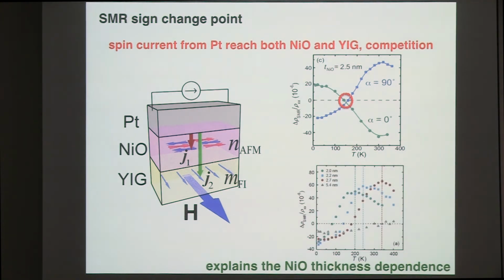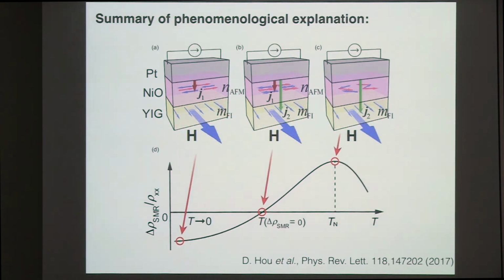What is very important is that this sign change point will change with the thickness. The reason is that if you have a very thin nickel oxide, it will become paramagnetic at pretty low temperature. So this zero point of SMR will be at a low temperature. If you make a thicker nickel oxide, this sign change point will shift to high temperature. So then we have a systematic understanding of this effect: the low temperature negative SMR is due to this spin flop coupling, and this compensation point is due to the competition between positive and negative SMR from YIG and nickel oxide respectively.